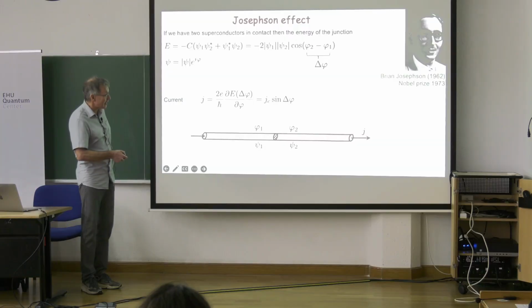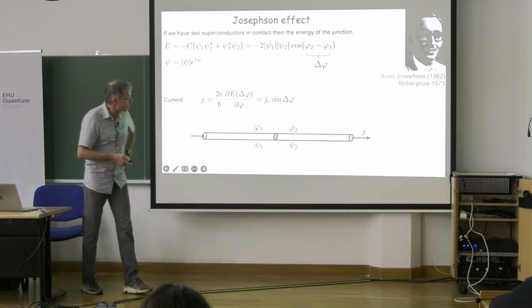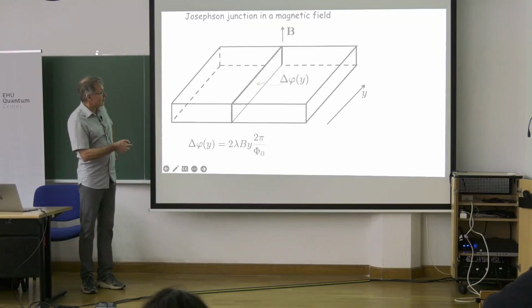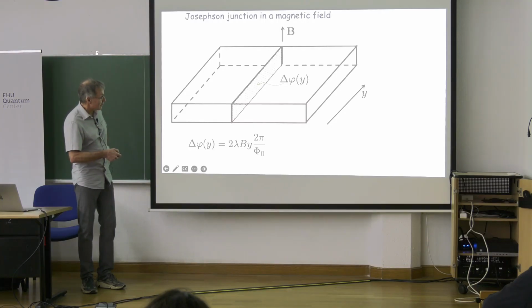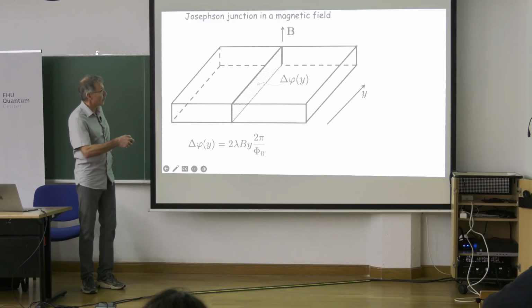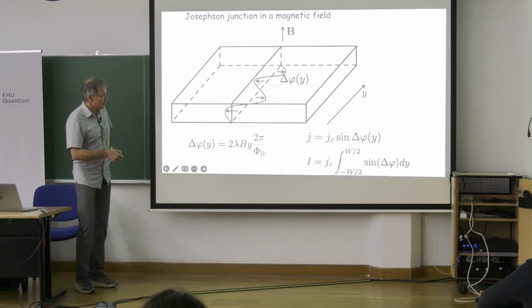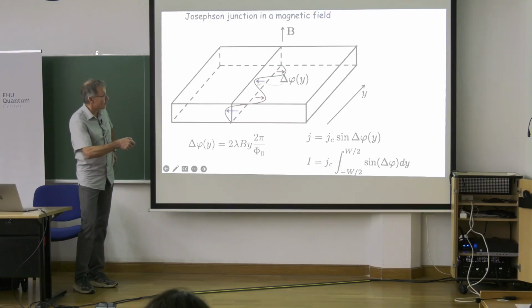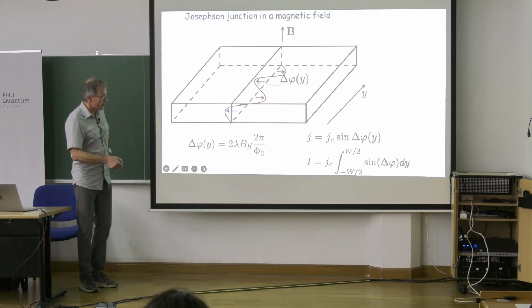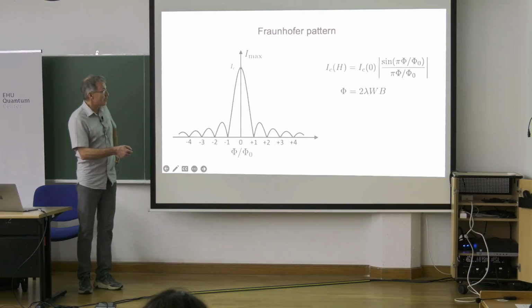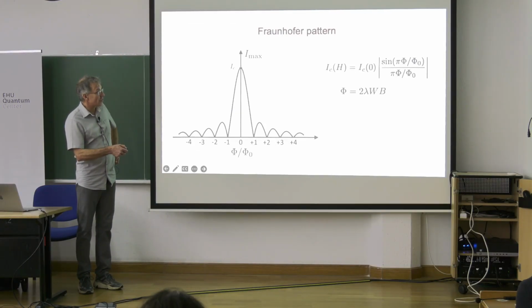So if you have two different phases, the current through the junction is sine of the phase difference between them. If you put it in a magnetic field, the magnetic field modifies the phase difference so that the phase changes linearly when you go along the junction. Current is sine of the phase difference, so current density would oscillate. Here current would flow from right to left, here from left to right, and so on. Total current is the integral of this, and when we integrate, the critical current is sine of flux through the junction divided by flux.